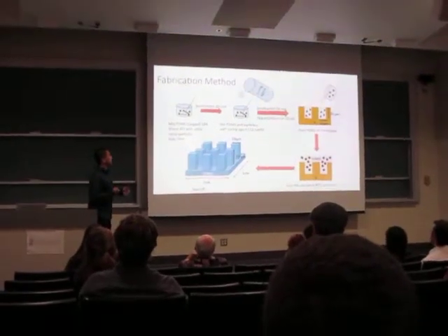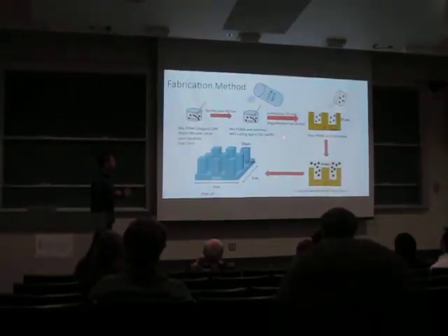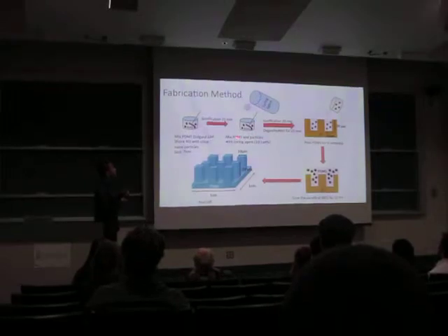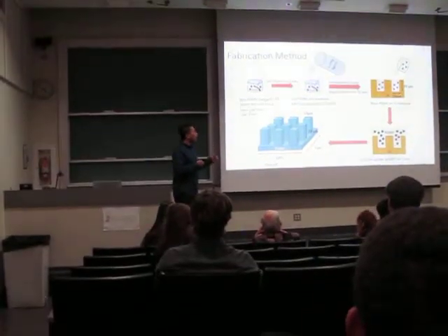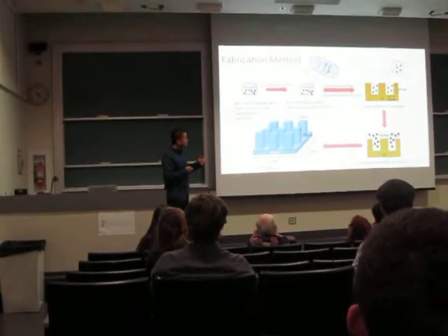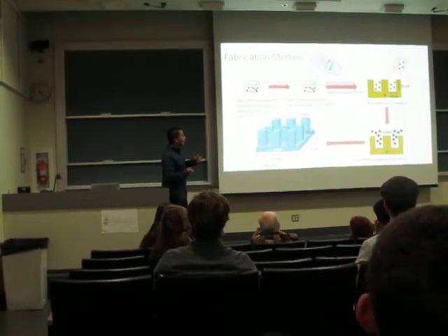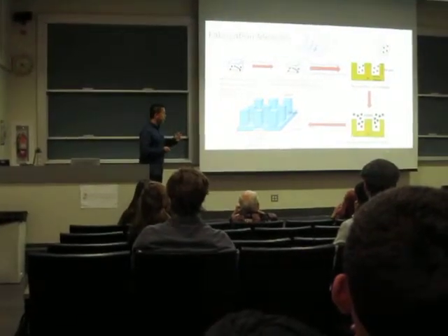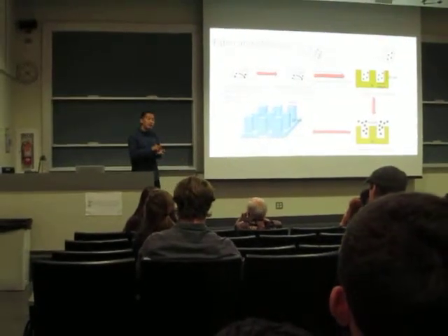So we go through the degasification process for 20 minutes. And after all this, we pour the PDMS sample onto a silicon template with all these holes. Then we cure at a temperature of 60 degrees C for 10 hours in the oven. After that process, we peel off the sample from the silicon template, and we have those